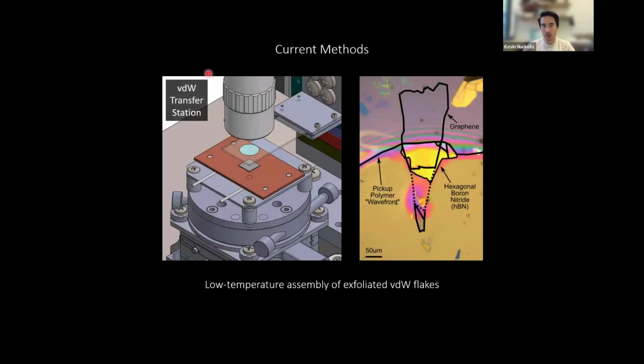So in the past decade, all of this research has been really pioneered by a really useful tool that we call the van der Waals transfer station. Because the van der Waals transfer station allows us to assemble exfoliated van der Waals flakes of many types at low temperatures. So this is a great tool for doing 2D research because it's highly versatile. Effectively, any 2D material that I can exfoliate down to thin flakes, I can produce a Moiré material out of it by twisting and stacking these.